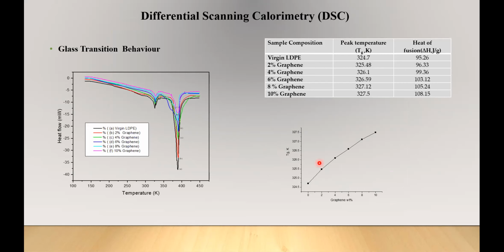Now we are going to the differential scanning calorimetry study. And in this case, we have used the 5 samples and the virgin material. You can see that this is where the glass transition temperature happens. And the peak value of virgin LDPE is shown at 324.7. We can round it as 325 Kelvin. This glass transition happens due to the partially ordered interface between the lamella and the amorphous region, and it is also known as glass transition or alpha transition of LDPE.